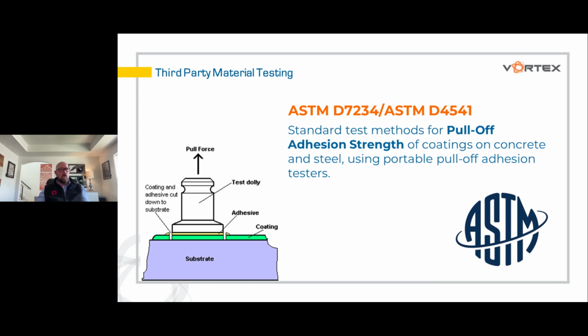And so typically what we want to see, and what you'll see in our materials, and you noticed that on slides earlier, is that when we're talking about steel itself, our materials create a plus 3,000 PSI bond strength to steel when the substrate is properly prepared. And to concrete, we typically are getting substrate failure. And when we're not getting substrate failure, we can get up into the 2000s range as far as the PSI goes.